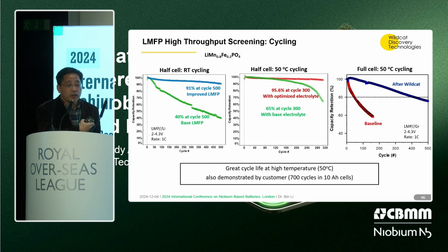Now, here's just a little data demonstrated for these materials in both half cell and full cell. For these materials, especially when you have a very high amount of manganese, the elevated temperature performance would be the key. Here we demonstrate at 50 degrees C in both half cell and full cell. Here, still with Wildcat high throughput cells, which are quite small cells, we demonstrate 400 cycles, but then this one was work with a customer, and they made a 10 amp hour pouch cell. They were able to reach 700 cycles at 50 degrees C. So this is critical for the LMFP at elevated temperature performance.